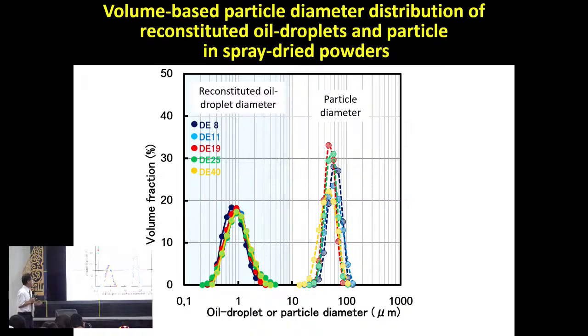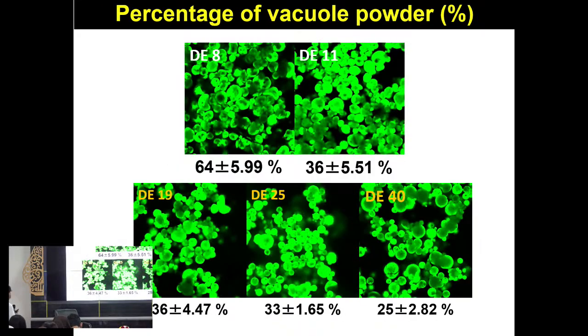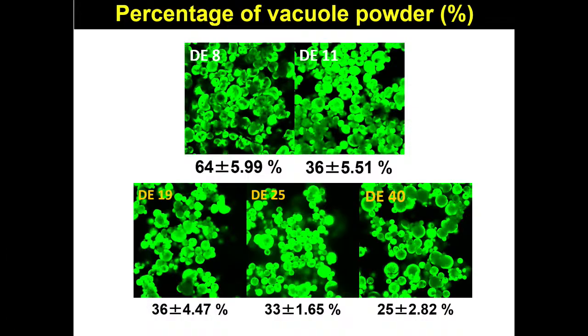So in this case, we make the same oil droplet, about 1 micrometer, and powder size about 50 or 60. So we make powder with the same oil droplet size and the same powder size. And then we check the percentage of vacuole powder using CLSM. Maybe the student counts the powders: we slice the powder by laser, and this powder has a vacuole, this powder has no vacuole. Maybe they counted 1,000 particles.